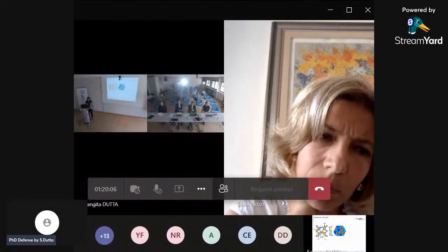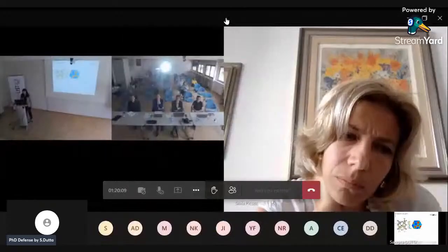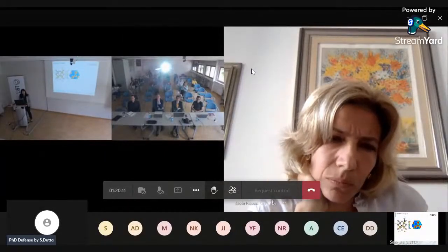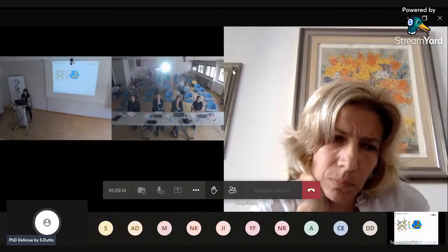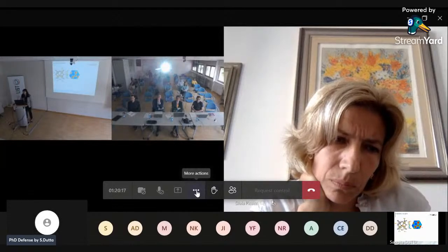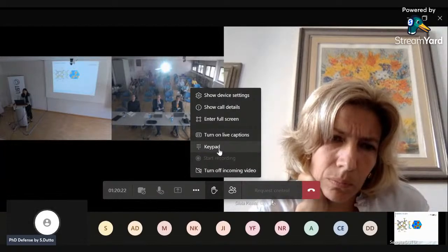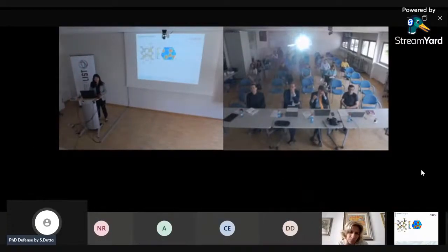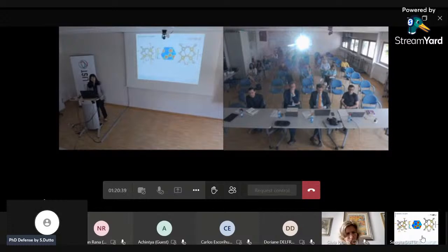So here I highlighted a few atoms, for example, this oxygen atom, which has three nearest neighbors. And as you can see from the bonding, it may look that they are almost similarly strong. So to understand that, we calculated the charge density distribution, and from this we can tell which bond is stronger. So they are almost equally strong. So now imagine that we are stretching the cell. How should this oxygen atom move? Should it move up or should it move down?